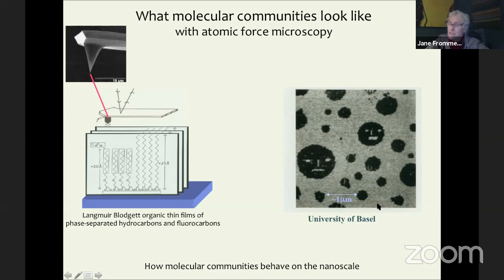The scanning motion goes over the molecules line by line, revealing how they separated on the surface. This image is about five microns across. We see dark islands in a light sea — those dark islands are the hydrocarbons, taller than the surrounding fluorocarbon sea. So when you make a mixture of these two molecules and put them on a surface, they separate as circular islands of hydrocarbons in a continuous sea of fluorocarbons. We also used the stylus of the atomic force microscope as a manipulator to create features — these instruments can both record information and manipulate surfaces.